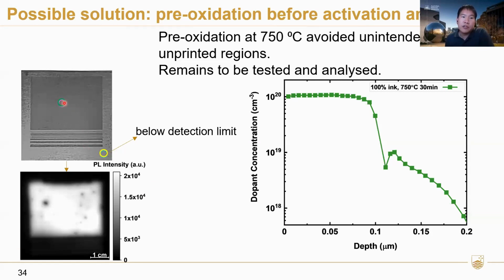We do the same process here. We measure the dopant concentration in the printed area, same as before. But now, if we do the oxidation and we measure the areas outside in the unprinted area, the concentration is actually below the detection limit. So I think this is a promising option for avoiding this cross-doping, but it definitely needs a bit more work to verify this.